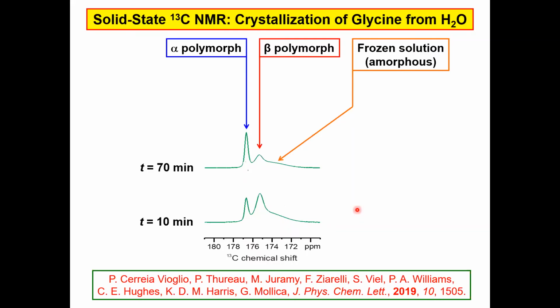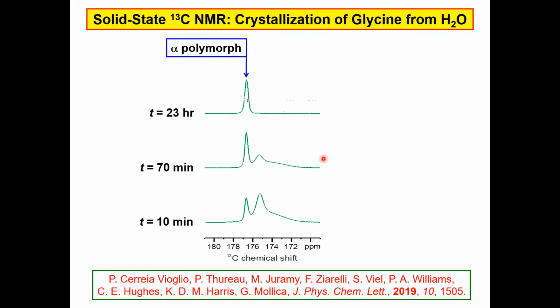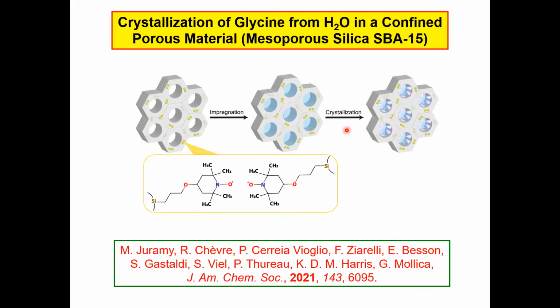As we go to a longer period of time, we can see the transformation of the beta polymorph to the alpha polymorph, and then at even longer time, we actually have only the alpha polymorph and no significant amount of uncrystallized glycine in this particular case. So this shows us how we can benefit. This is really just touching the tip of the iceberg of what was done in this study, but utilizing DNP in this area of exploring crystallization processes.